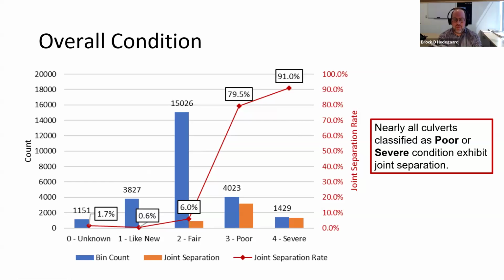However, we did want to see what that correlates to in terms of the overall condition of the pipes. So once again, similar idea, the blue is going to be the count of each bin. And so this is based on the condition number that's given to those pipes in that database. 0 being unknown, 1 being a like new pipe, and then 4 being the worst case, a severe pipe. And to no surprise, pipes that have a low condition rating, or technically a poor condition rating, poor or severe, are going to have a very high incidence of joint separation.